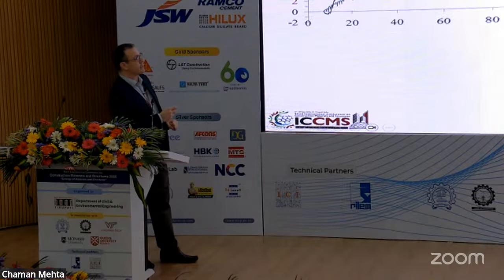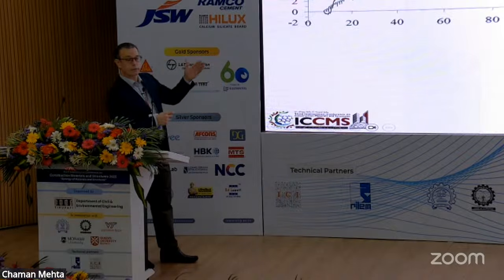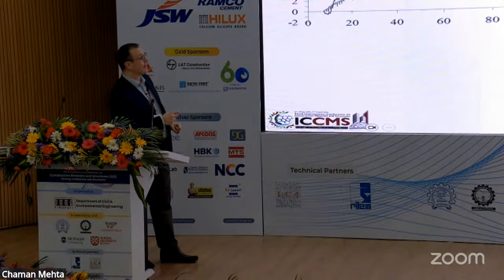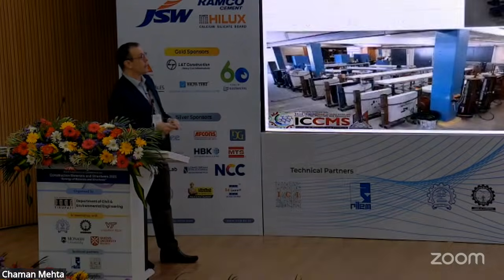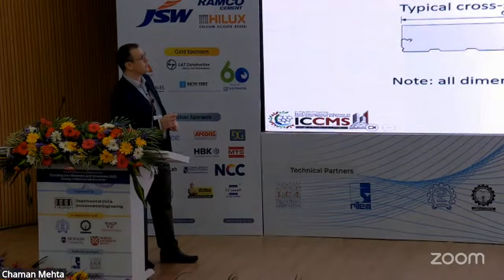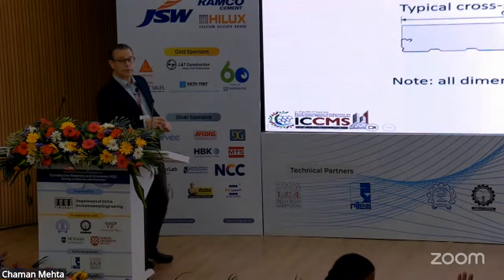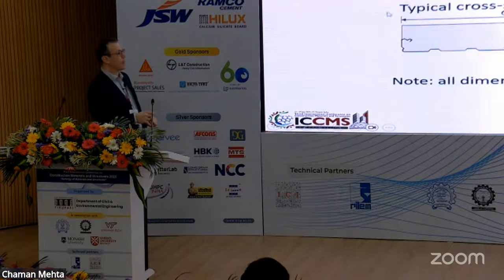Again, in this case, if you apply the uniform shrinkage that you would usually use if you were not thinking of the shrinkage gradient, you will be completely underestimating the deflection. You will be quite a lot way out. And you saw in the test before, we just had the solid slab and additional slabs. As a final remark on this domain, if you look now at composite slabs, simply supported and continuous, we have the same profile. All we change now is the drying condition, the surface condition on the top.